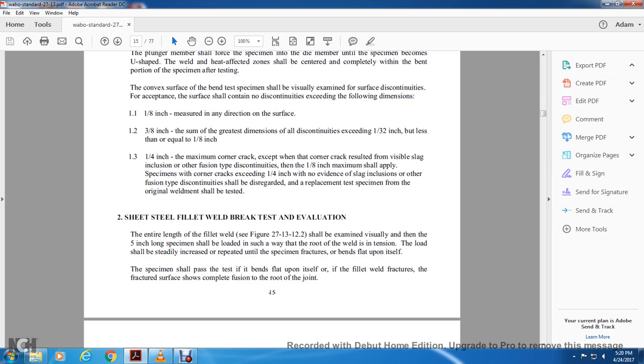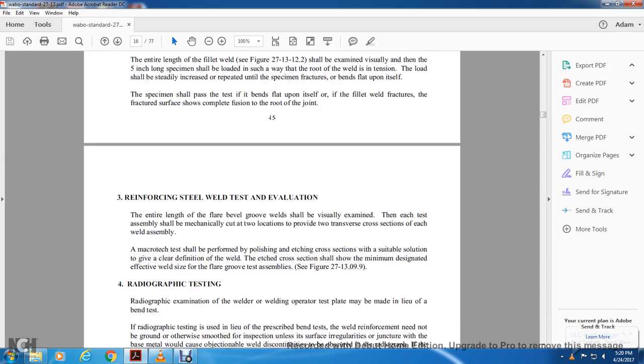Two. Sheet steel fillet weld break test evaluation. The entire length of the fillet weld, see Figure 27-13-12.2, shall be examined visually. Then a five inch long specimen should be loaded in such a way that the root of the weld is in tension. The load shall be steadily increased or repeated until the specimen fractures or bends flat upon itself. The specimen shall pass the test if it bends flat upon itself, or if the fillet weld fractures, the fracture shows complete fusion in the root of the joint.